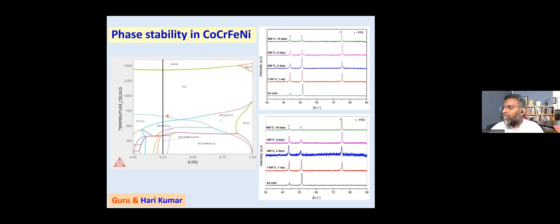There are thermodynamic reasons why this happens. But what is interesting is, if you make this alloy by the casting route, you see this alloy has a single phase FCC at room temperature, please note it. That means something is happening. That means this segregation, or phase separation, that we are talking about has not happened for some reason. And that is the second problem that I'm going to talk about a little later. We also heated this alloy to various temperatures to know whether it is stable as a single phase or not. Even at 600, 700 degrees or even 800 degrees, it is always a single phase. Even long hours of heat treatment show that it is still a single phase.